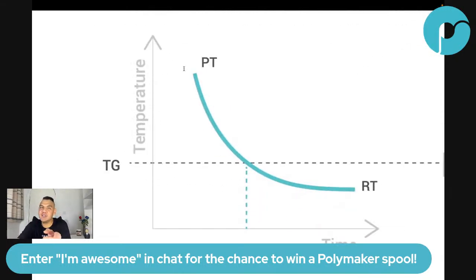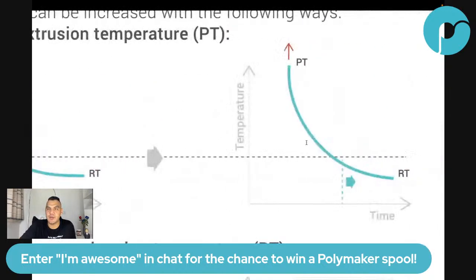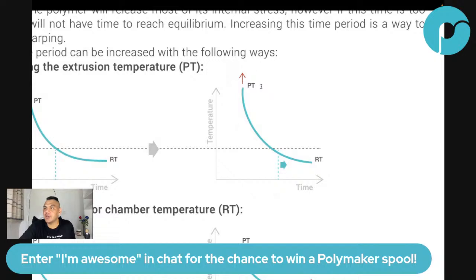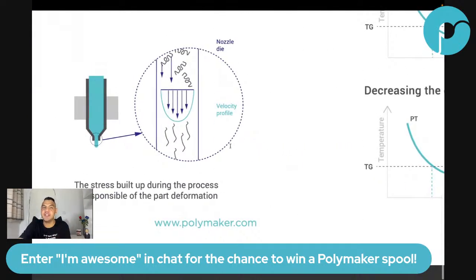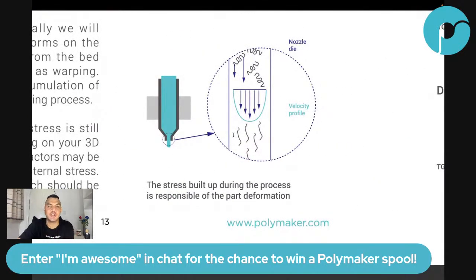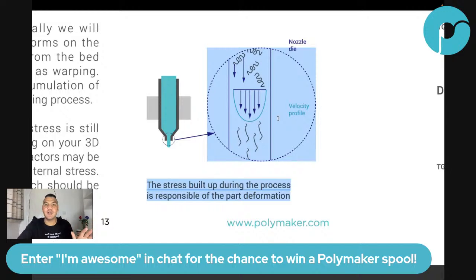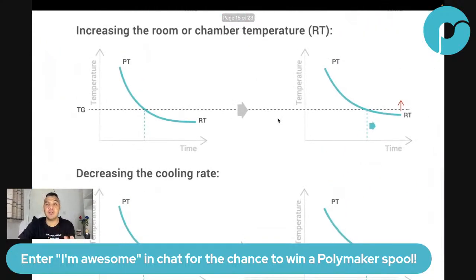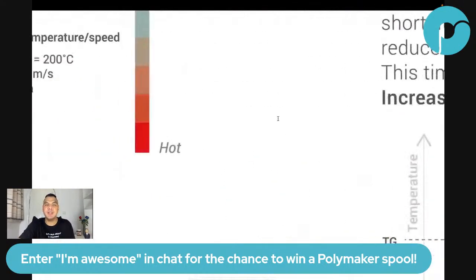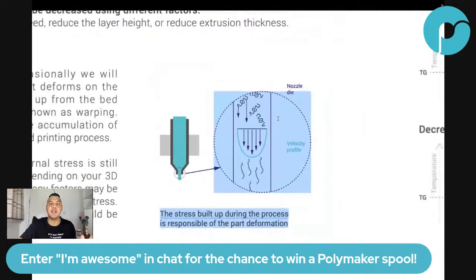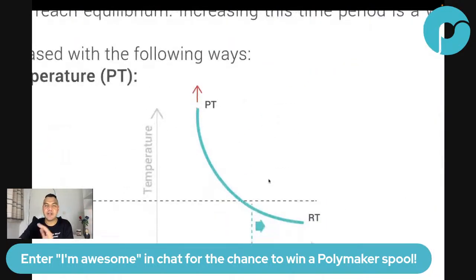And then if you increase the printing temperature, what's happening? You can see on the chart that you are increasing the time at which the polymer is staying above TG. So you are releasing more stress. Before, we were talking about how to limit that stress, how to not create too much stress. So before, all the solutions we had were about not stressing the polymer or stressing it the minimum possible. Now, the solution we're talking about is: okay, we have that stress, we minimize as much as we can with some solution. Now, that stress that is left, how can I get rid of it?